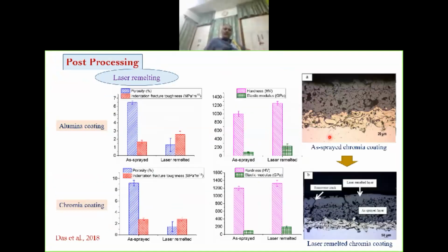Next, post-processing. Simple. We had a coating, very porous. Melt the top layer with laser. Big defects, cracking will be there, but pores will go. Porosity initially was 6%. After that, it's reduced. After laser remelting, the indentation fracture toughness also improves. Hardness increases, so does the elastic modulus. A similar observation was made for chromia coating, not only aluminum oxide.